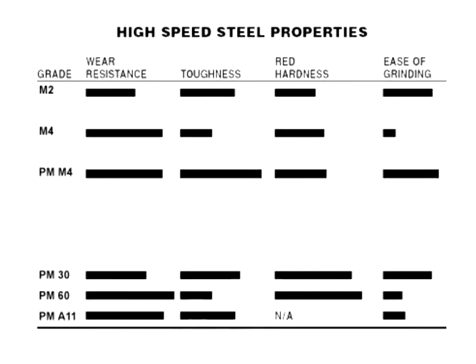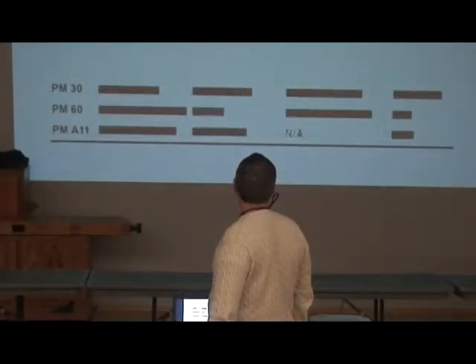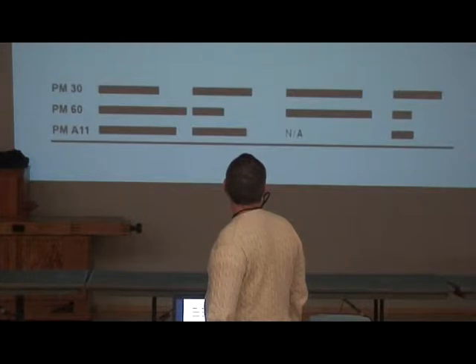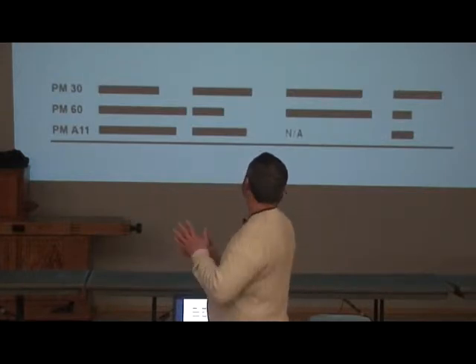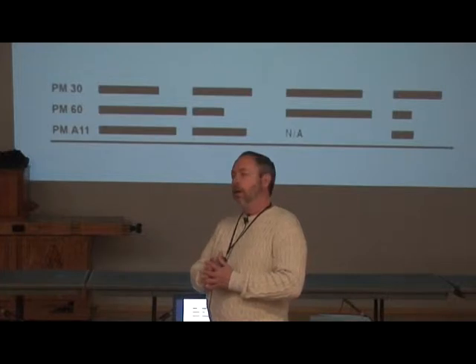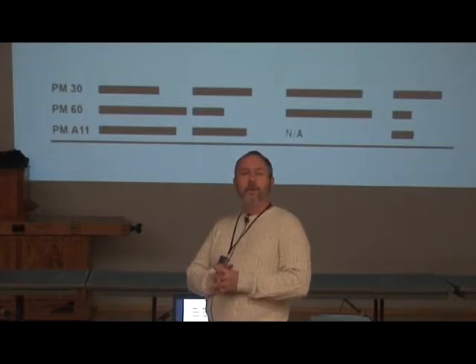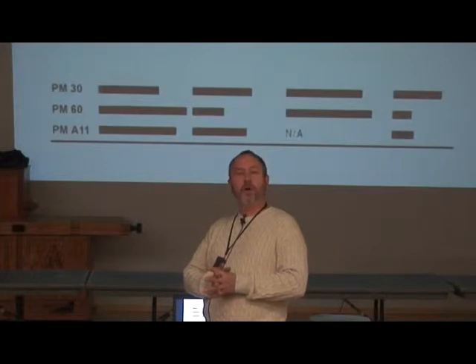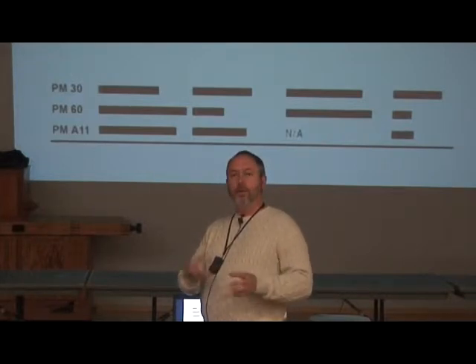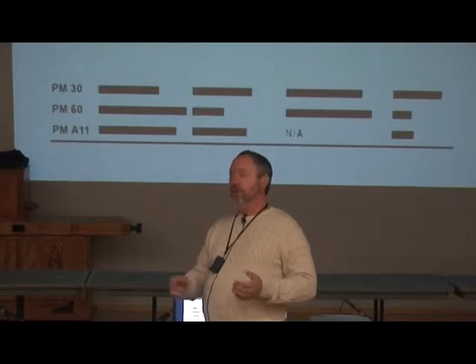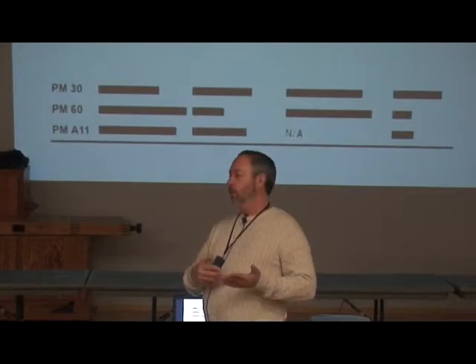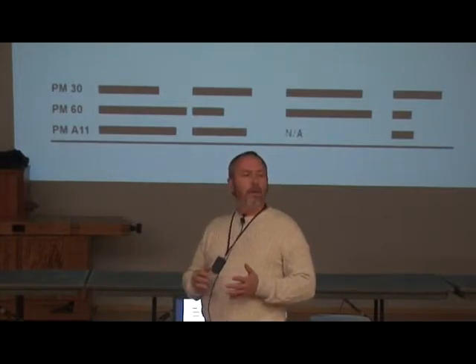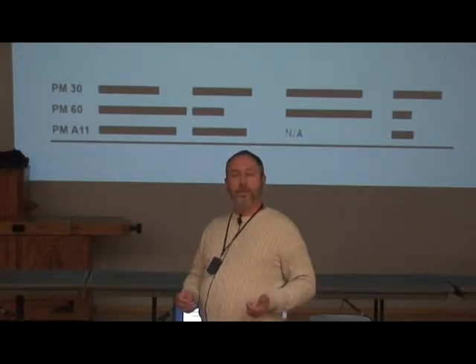Basic chemistry, just different. Then ease of grinding. M4 isn't the best. Powdered metal M4 looks pretty good. Now the reason the powdered metal M4 grinds so well is the carbides in it are very small and uniform. You don't have big chunks of carbides in there. They're very small, very fine, so your tool can actually cut them well, but when you're running them against wood, etc., they're very abrasion resistant.